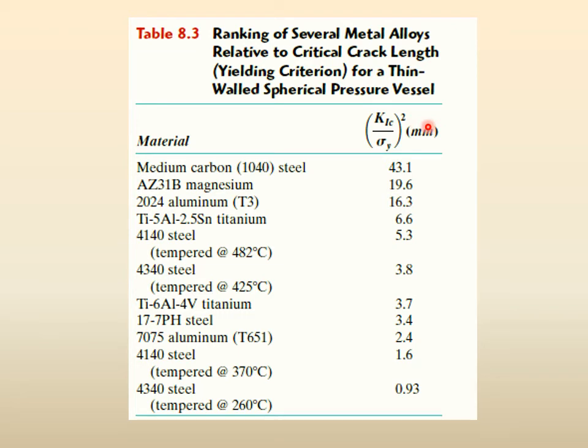So from 1 millimeter, for example, if you can go to 43 millimeters, there is a large amount of deformation before it can fail. But if you have to go to only 20 millimeter before it can fail, or only 5 millimeter before it can fail, right? So this is your best material, this is second best, third best, and so on. So this is it, right?